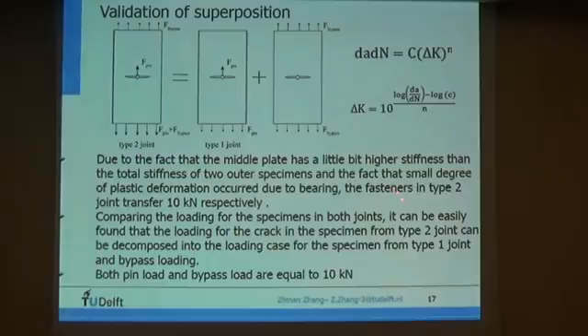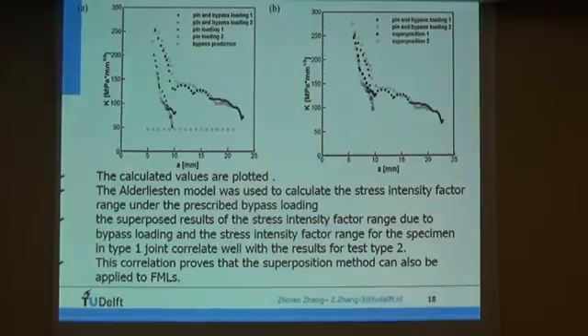And so the fastener in type 2 joint transfers 10 kN respectively. Comparing the load of the specimen in both joints, it can be easily found that the load for the crack in the specimen from type 2 joint can be decomposed into the load case for the specimen from type 1 joint and the bypass loading. Both the pin loading and the bypass loading are equal to 10 kN. So that's the result. We calculate the data of the test.